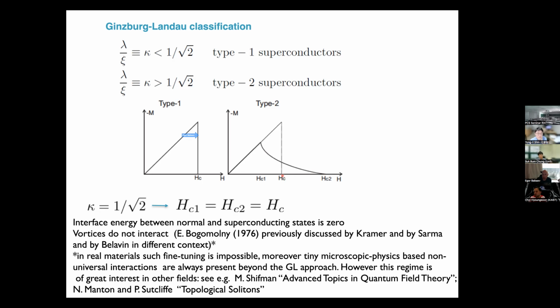And if you have negative interface energy, superconductivity can persist above the thermodynamical critical magnetic field, and that's because you have some objects with negative energy, when you phase separate into a superconducting state and normal states living in the vortex cores. You can think about it in that type of framework, as objects having negative free energy, and that allows superconductivity to survive above the thermodynamical critical magnetic field associated with the uniform state.